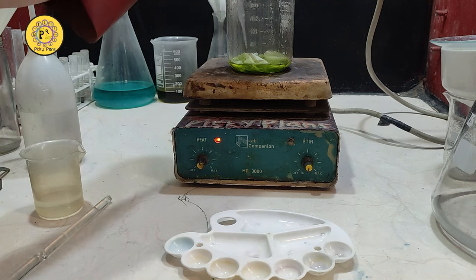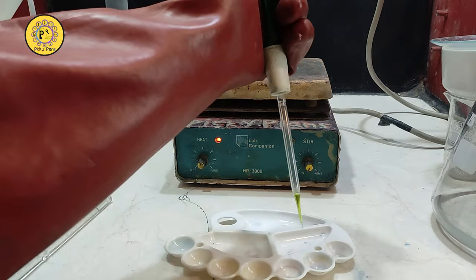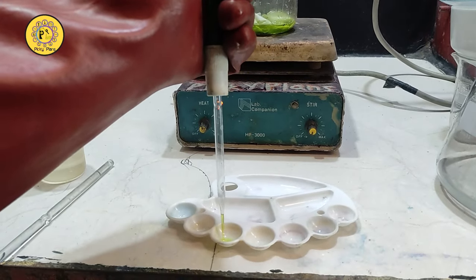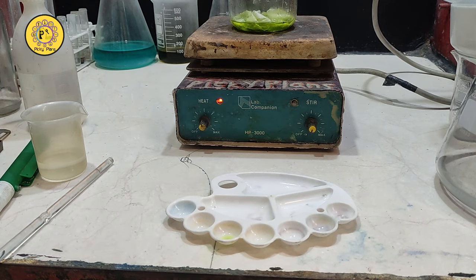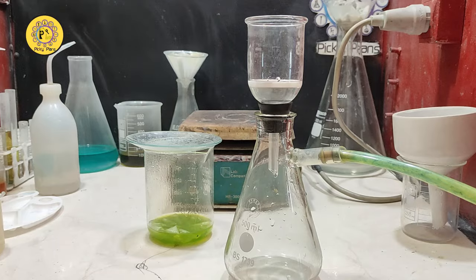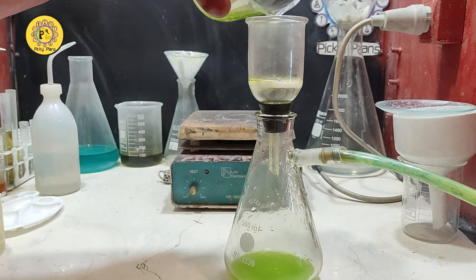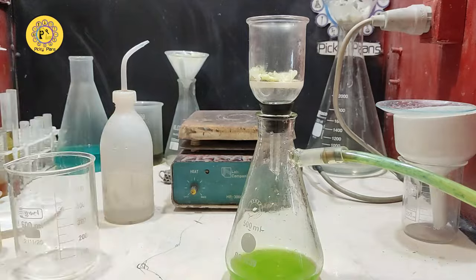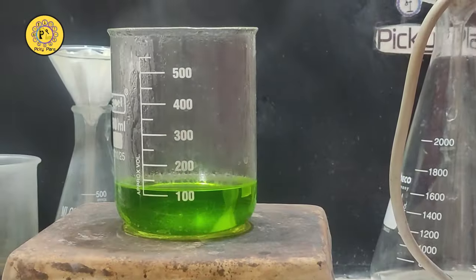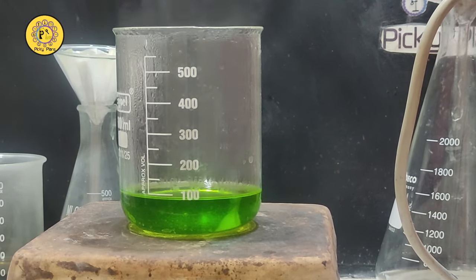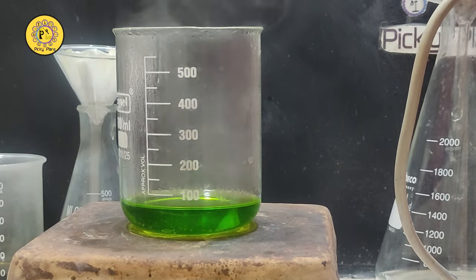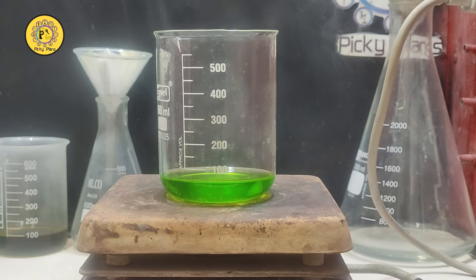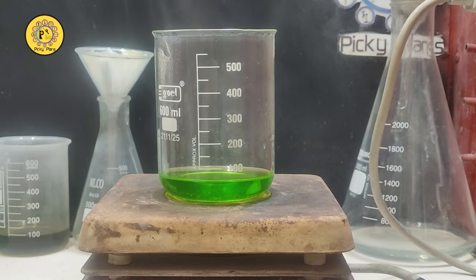Now let's test the solution with stannous chloride to see if we actually get any gold from this. Yeah, the test is positive and we got the gold. Filtration was repeated a few times, just in case, to get a clean drop out of the solution. Due to washing the filter papers, the solution got diluted, so I placed it on the hot plate to evaporate some water. Some sulfamic acid was added to kill remaining nitric acid. Then I added ferrous sulfate, letting it sit in there, no stirring, to grow gold on the ferrous sulfate crystals.